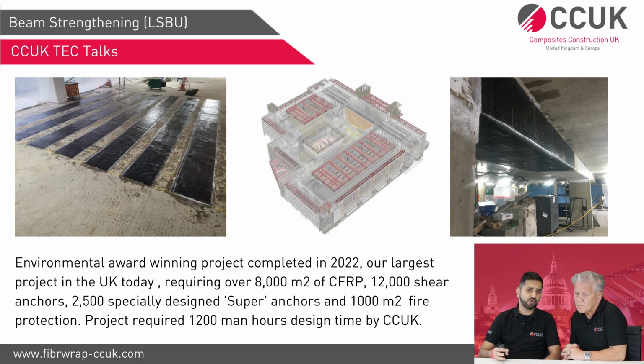The reason for the award was that it's actually the structural engineer who won an award from IStructE on this, in the sustainability category. The reason for that is that by using CFRP, the CO2 emission on this particular project was just 49 kg CO2 per square meter, as compared to the 105 kg CO2 per square meter LETI target for 2030. So they managed to do it, and for that reason they won the award.